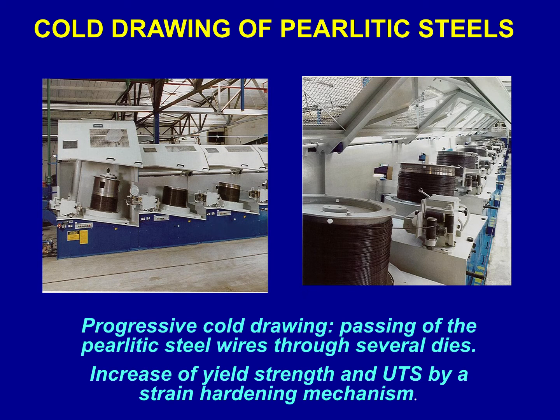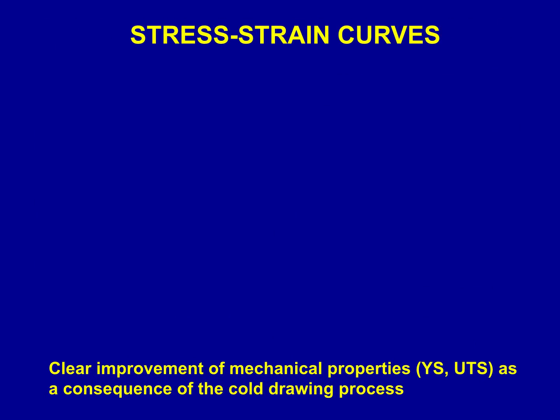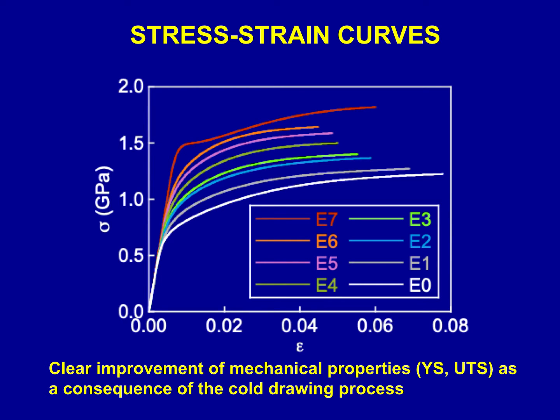Here I am showing 2 pictures of a real cold drawing process of pearlitic steel to manufacture commercial pre-stressing steel wires. There is a progressive cold drawing, passing the pearlitic steel wires through several dies, and the main consequence, the final aim of manufacturing, is an increase of yield strength and ultimate tensile strength by a strain hardening mechanism. The stress-strain curves reflect this process of strain hardening, with a clear improvement of mechanical properties, yield strength and ultimate tensile stress, as a consequence of the cold drawing process.